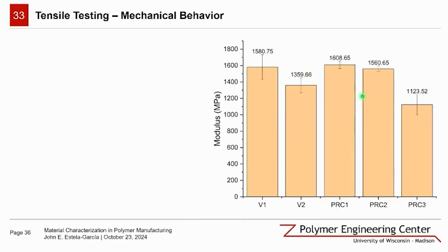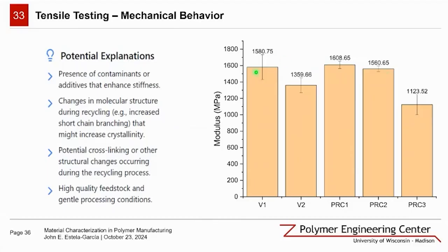Here from our tensile test results, we have some interesting findings, in my opinion. Contrary to what I would expect from samples with higher MFI and lower viscosity molecular weights, the PCR1 and PCR2 exhibit surprisingly high moduli comparable to the first virgin sample. Several factors could be at play here. It could be the presence of additives that could be used to enhance stiffness. The recycling process itself could induce changes in molecular structure,